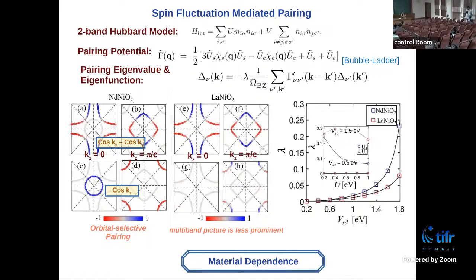Okay, so two things I wanted to know. One is that the gap that you are getting, how does it depend on U? Yes, I rushed through it. You can see that this lambda, which is the strength of the superconductivity, is shown here as a U dependence. It is not very strongly dependent on U, but it is strongly dependent on V. I see. So you need a certain value of U, otherwise it will not show up, but after U crosses a certain value, the variation is not so much. On the other hand, V has a tremendous effect. Okay. The other thing is that from these plots, it looks like these are not effectively two-dimensional systems. No, these are not. That's why we are saying it's not like cuprate. It's not at all a two-dimensional-like system.